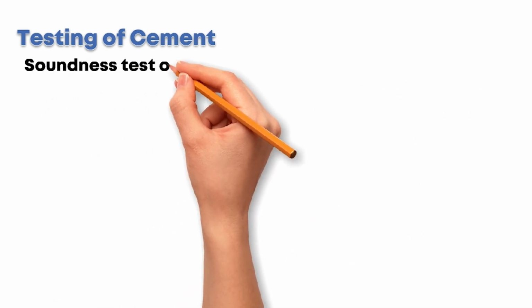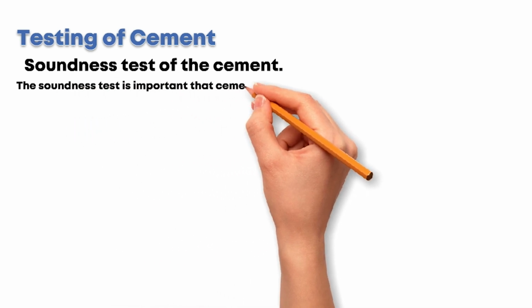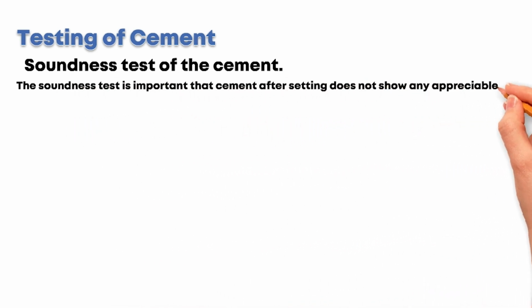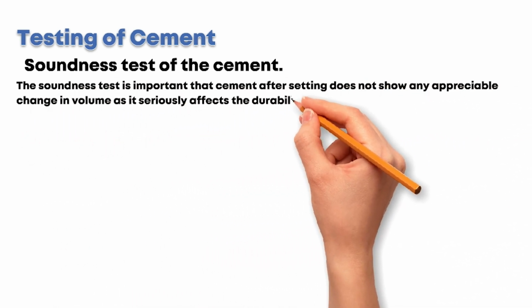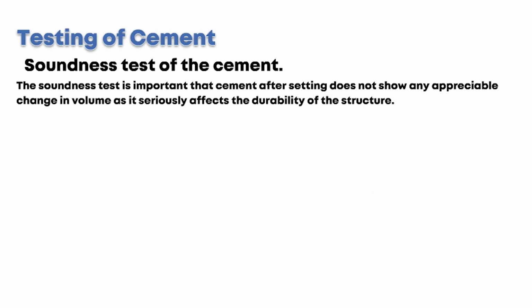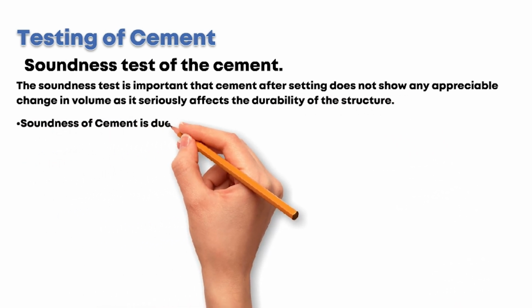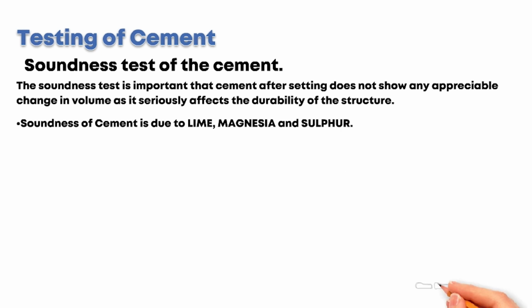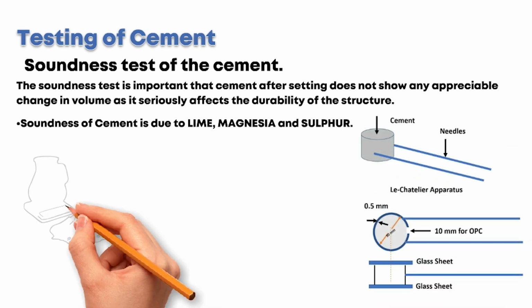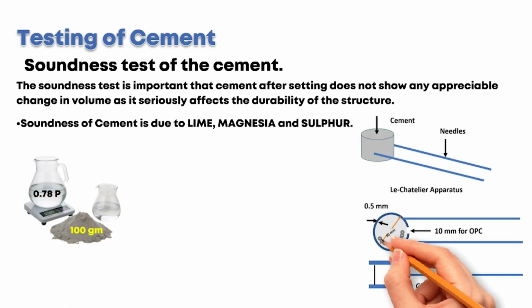Let's discuss the soundness test of the cement. The soundness test is important, as cement after setting should not show any appreciable change in volume, as it seriously affects the durability of the structure. Unsoundness of cement is due to lime, magnesia, and sulfur. Gauge 100 g cement with 0.78 times consistency and fill the paste in the mold.